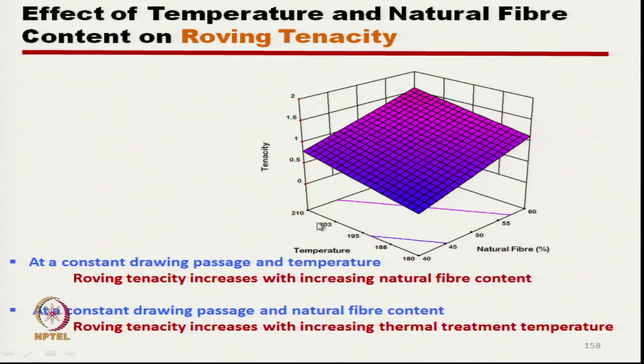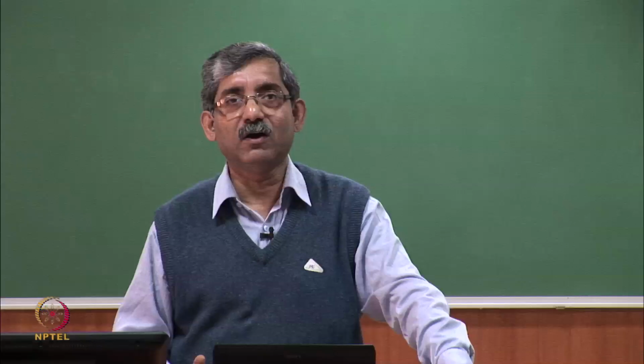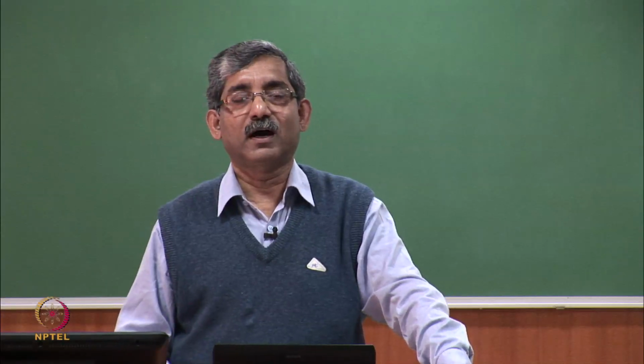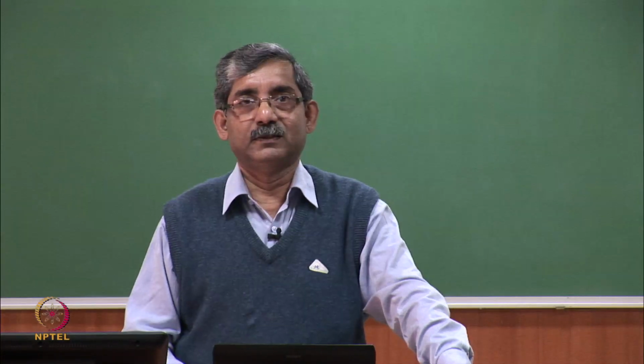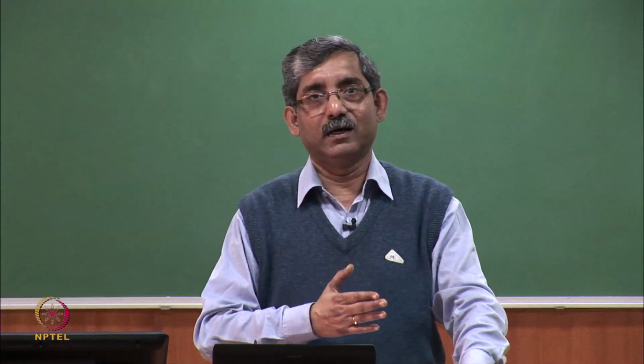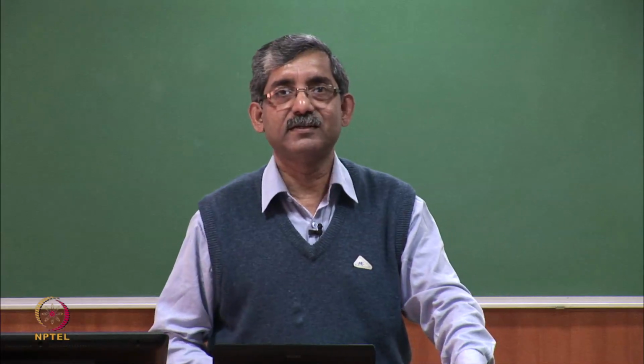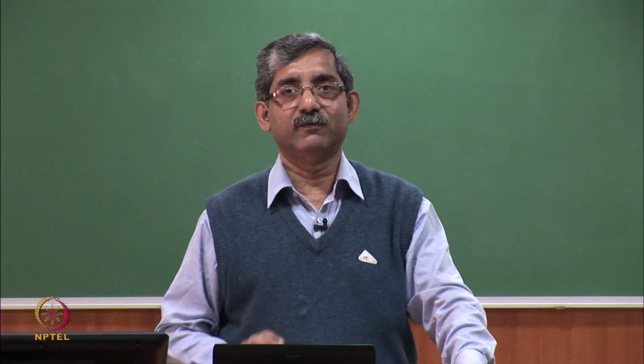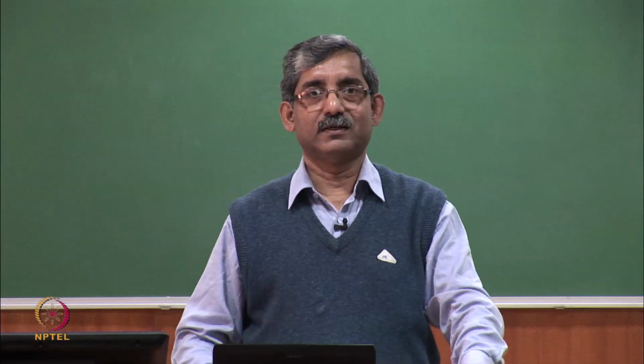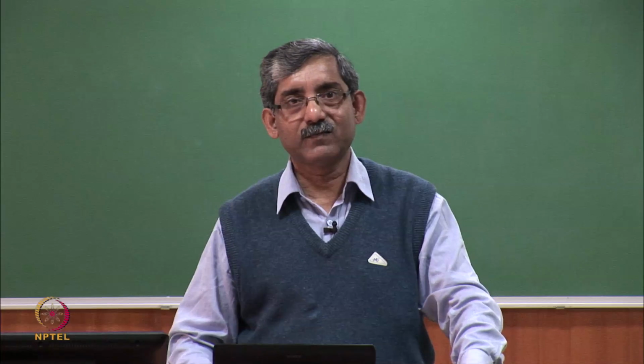Now, if you see this axis here at constant drawing passage of 6 and natural fiber content, say 40%, roving tenacity increases with the increasing thermal treatment temperature. That means proper melting of polypropylene is there. So, similarly, we can have different trends for different parameters. So, I will go quickly.